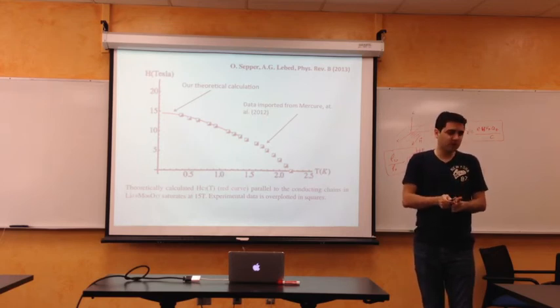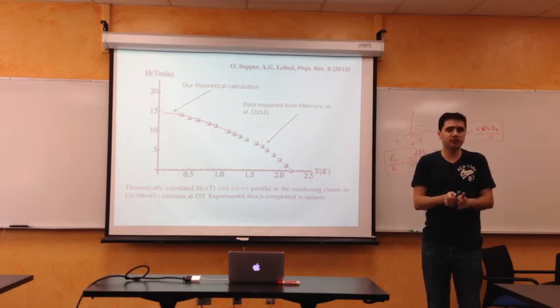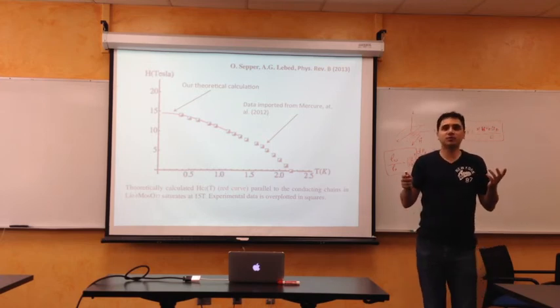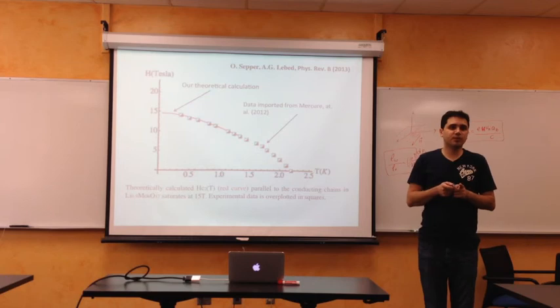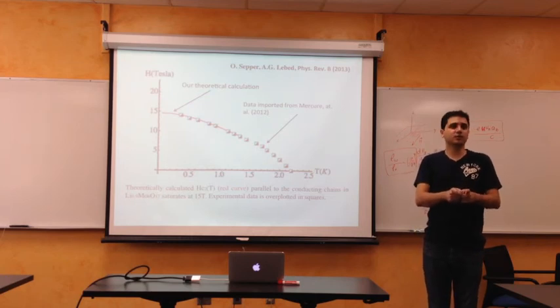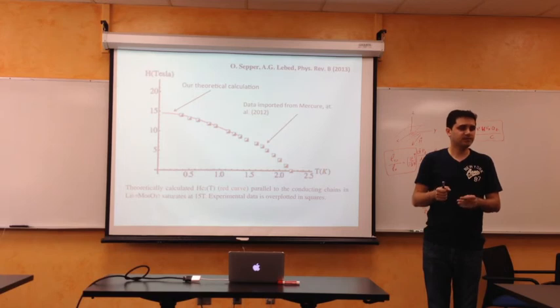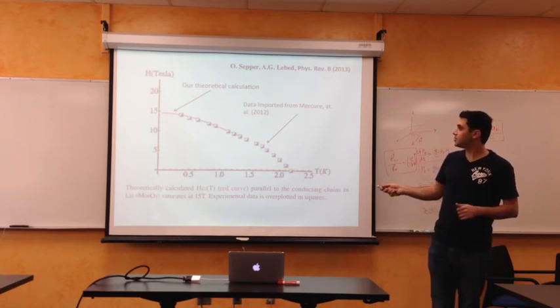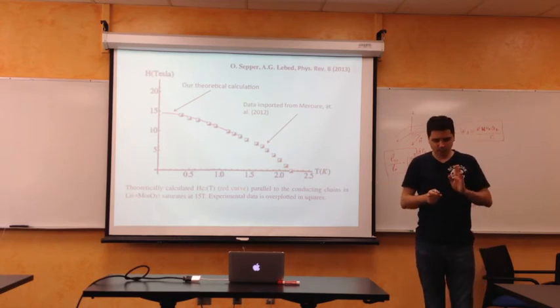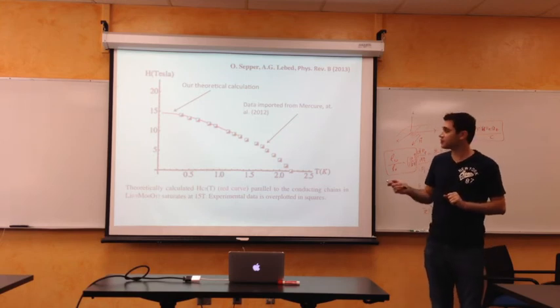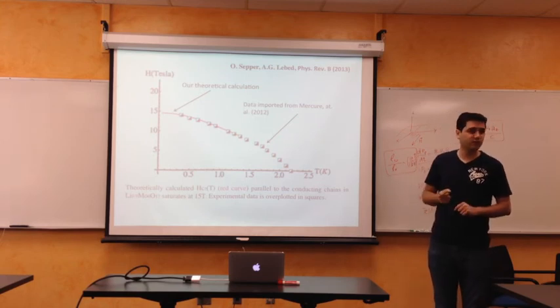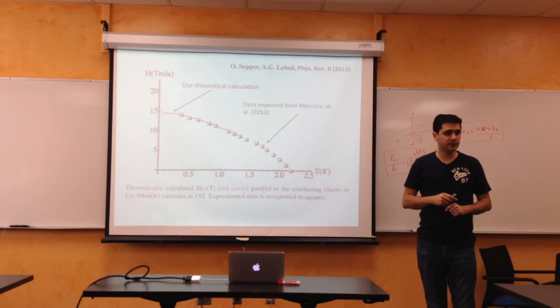I mean, when you have V cross B to be zero, Lorentz force is zero. So the counter argument was you cannot destroy superconductivity with a parallel field. The only thing that can kill it is paramagnetic effects. But as you can see, parallel orbital effects can frustrate the order parameter enough to choke the superconducting state out.